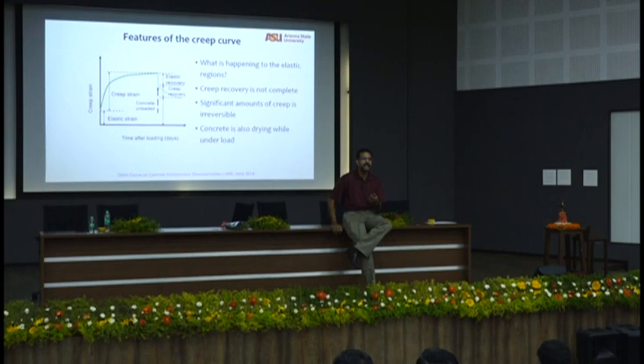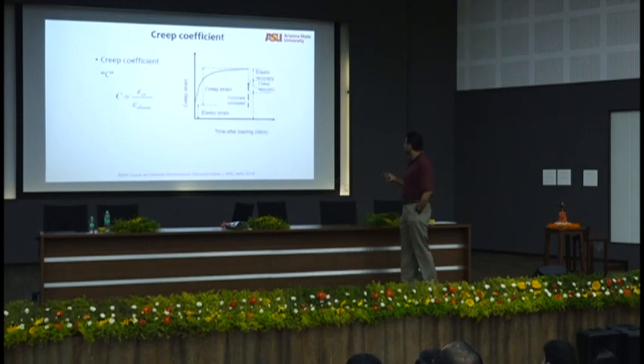Right? So again, the idea of limestone: good idea because limestone is soft. It reduces elastic modulus of the paste. It gives you good reaction products and strength. So materials like that, fly ash, slag, are good because these are of lower density than cement, and when they react, they'll give you a little less stiff paste. Okay, so creep has also to be very carefully taken into account. Creep coefficient, creep strain, I'll skip all of that.